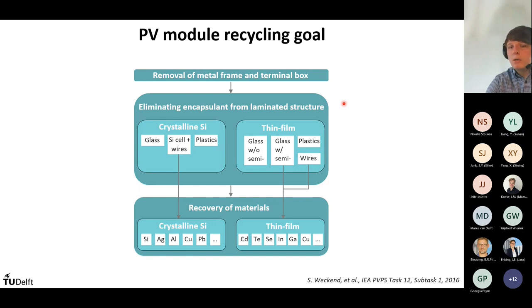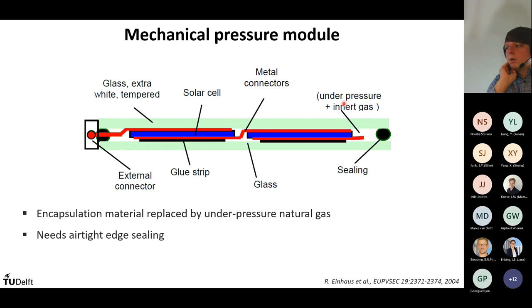And now, to give maybe more of an outlook, what could design for recycling look like? There is this mechanical pressure module, or NICE module, which was proposed in 2004. Basically, in between the cells, we have an under-pressure natural gas. This means that it has to be airtight, and it's essentially a technology similar to double glazing windows, where you have two glass layers with an under pressure, which are sealed at the edge. The only difference is that we need PV cells in between. In terms of thickness, the edge is maybe 0.5 millimeter. They are glued to the glass, and then you need to extract the current. So the edge seal needs to be airtight, but still have cables going through it.